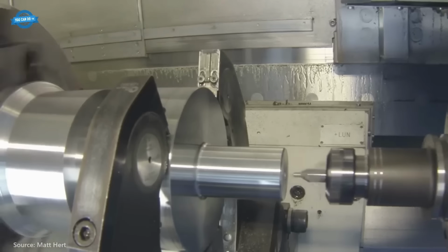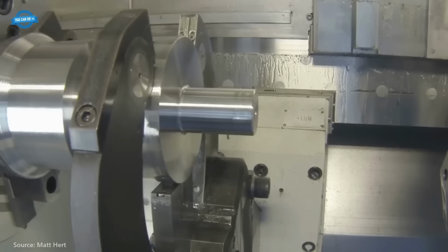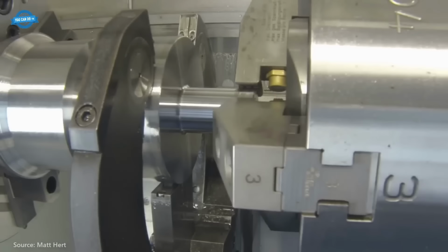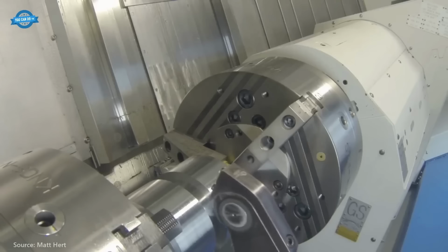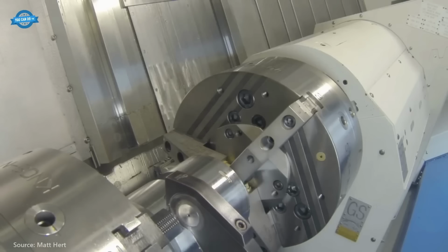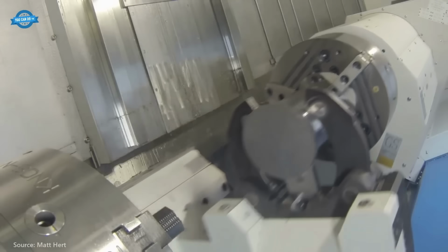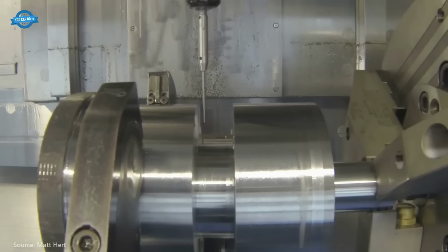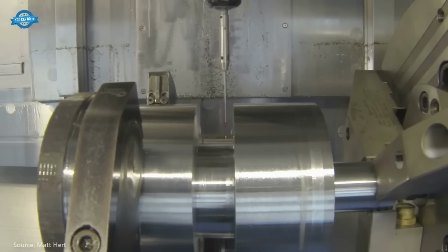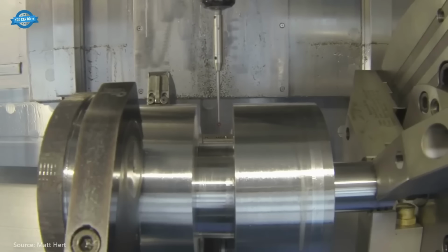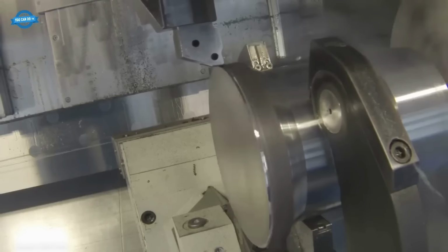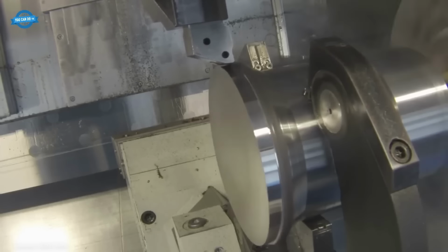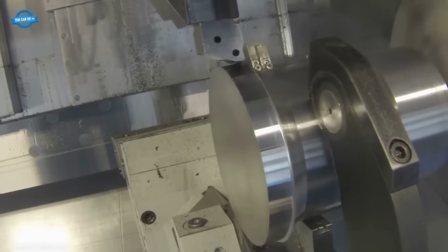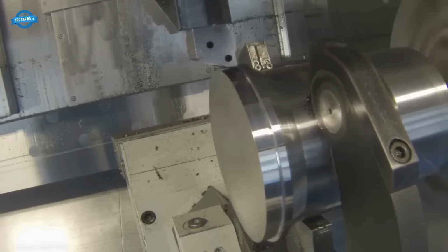Heat treatment and stress relief. To enhance durability, induction hardening is applied to specific areas such as journals and fillets, improving wear resistance. Tempering is performed to reduce brittleness while maintaining the required hardness, HRC 55 to 62. The heat treatment process, including cooling, generally takes 2 to 4 hours.